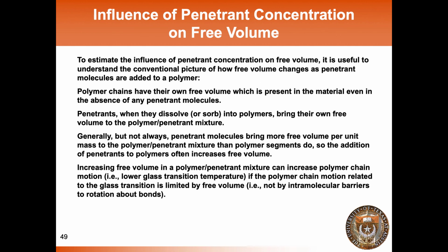If you start to put penetrants into that polymer, the penetrants bring their own free volume. And in rubbery polymers at least, you'll remember that you dilate the polymer matrix with every penetrant molecule you put into it, you swell it. And this is then going to change the free volume in the polymer. Often the penetrants will bring more free volume per unit mass than the polymer has. It's not always the case, but it's often the case.